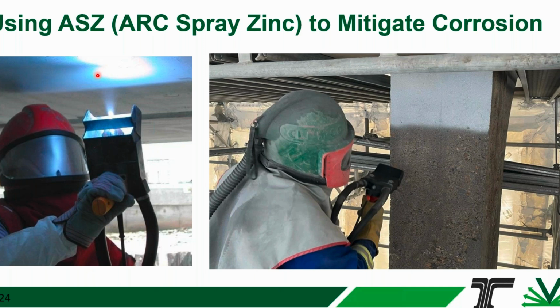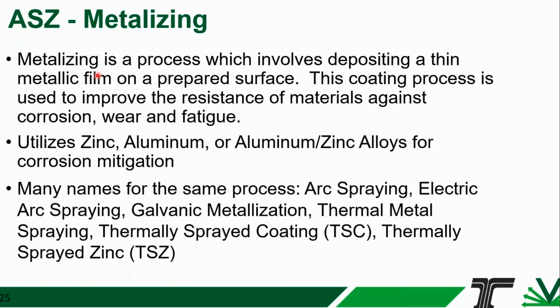And so basically we're applying a thin layer of metallic zinc onto the prepared concrete surface. Normally this is done with pure zinc, but in some cases aluminum, not very often aluminum by itself, but aluminum zinc alloys are sometimes used as well. And there's lots of different names for this process: arc spraying, electric arc spraying, metallization, thermal metal spraying, etc.